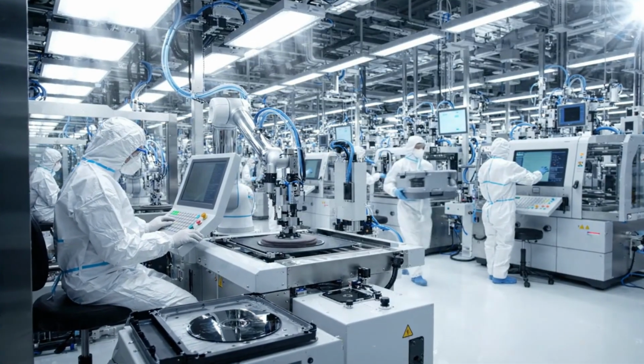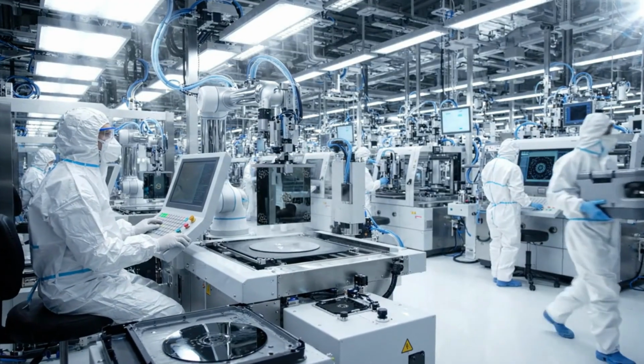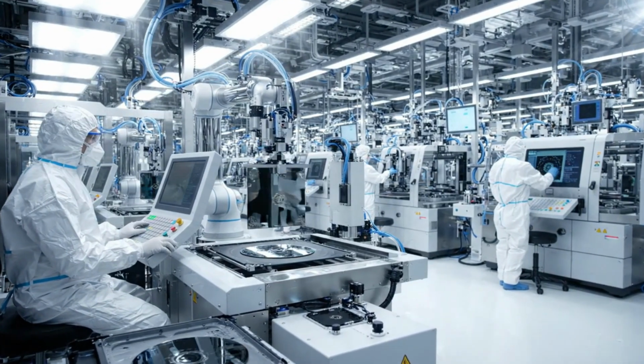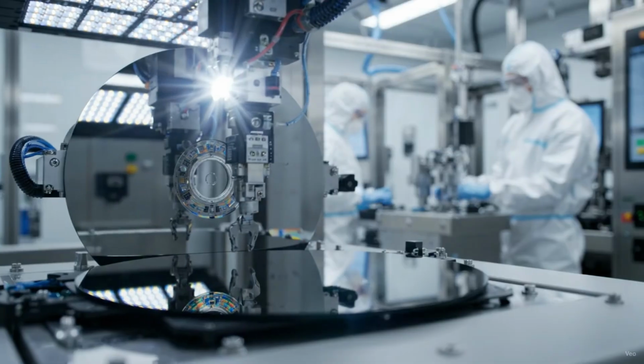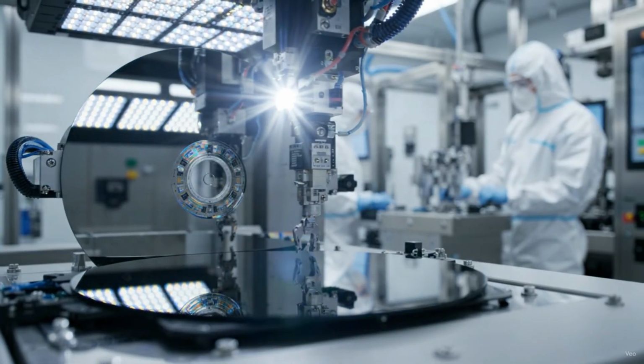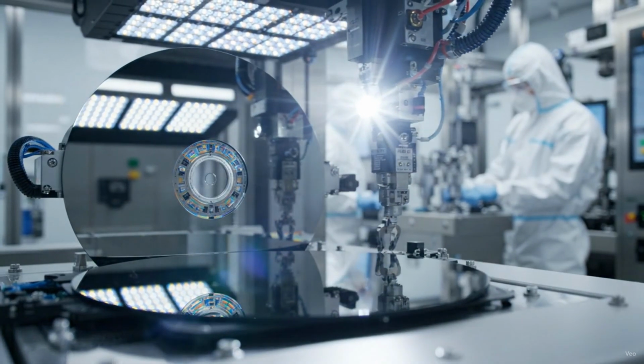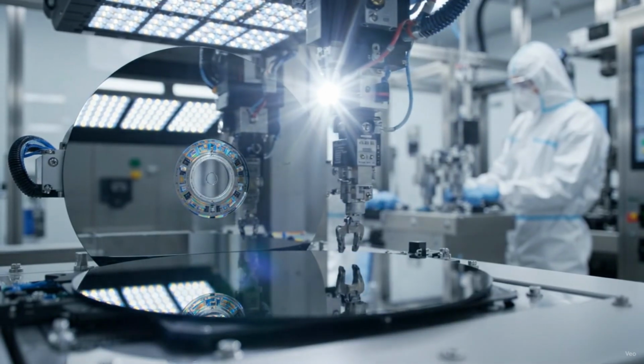Chemical-mechanical planarization creates a surface so perfectly flat that the variation across the entire 300-millimeter wafer is less than 1 nanometer. The finished wafer surface must be absolutely perfect. A single particle of dust is thousands of times larger than the transistors that will be built on this surface.